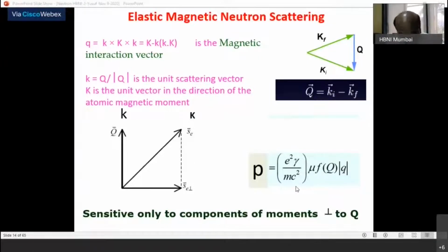See, X-ray being electromagnetic radiation, there is another field vector which is called the magnetic field vector. So E and H. But what happens is in any electromagnetic radiation, as you know, amplitude-wise the electric field vector is about 2 orders of magnitude stronger. So the magnetic field vector is about 2 orders of magnitude weaker than the electric field vector. So when you do the scattering experiment, cross-section wise it is 4 orders of magnitude weaker, because amplitude-wise 2 orders, so cross-section wise 4 orders of magnitude weaker.